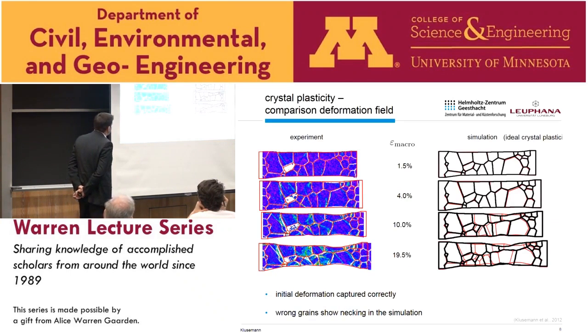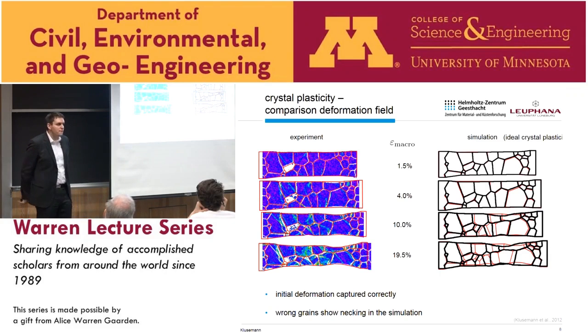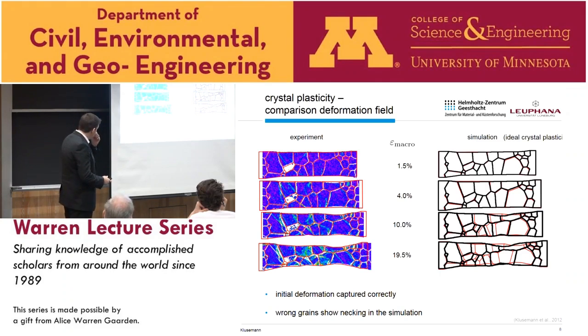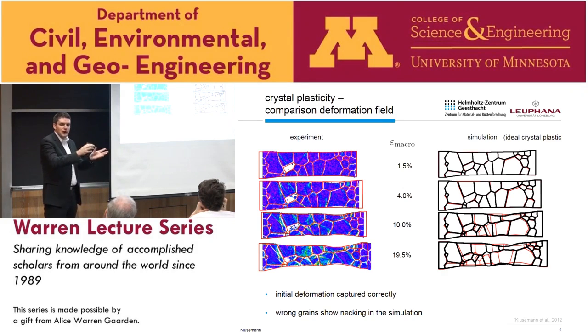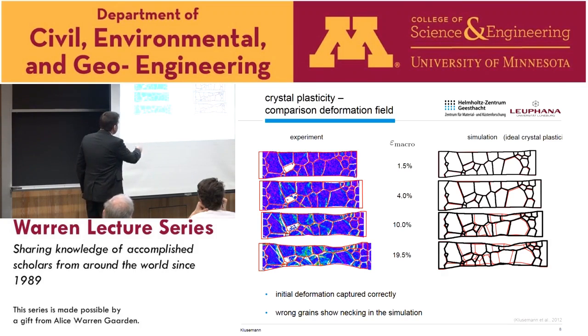Okay, so what we did first, we investigated the deformation field. And we had the problem for this iron silicon, we didn't really have enough material data, at least not from the single crystal level. So what we thought, well, let's see, first of all, what is the influence of the initial orientation of our grains. So we assumed an ideal crystal plasticity model, so no hardening on the glide system level, just an initial yield strength, and of course we're accounting for the orientation of each of our single grains. On the left side you see the experiment, and the red lines are an approximation of the deformation field to have a comparison to the simulation. And what you can see here on the right is then the simulation results in black, and of course in red is the experiment. Well, no, other way around. Let's see. Yeah, it's right here.